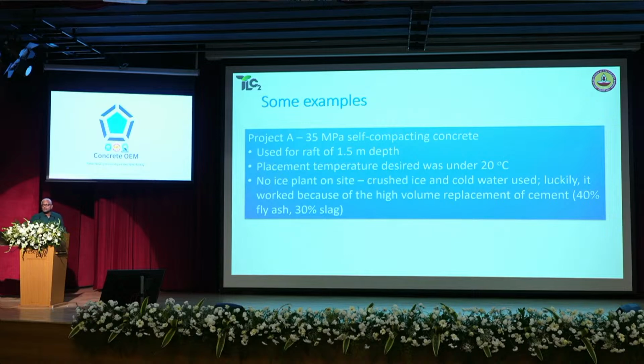Luckily here, because the cement was replaced massively by fly ash and slag. 70% cement was replaced, 40% by fly ash, 30% by slag, because of which, even with this control of the water quality, of the water temperature, we could still manage the concrete to be less than 20 degrees Celsius.